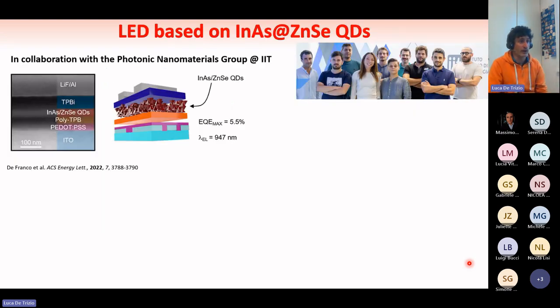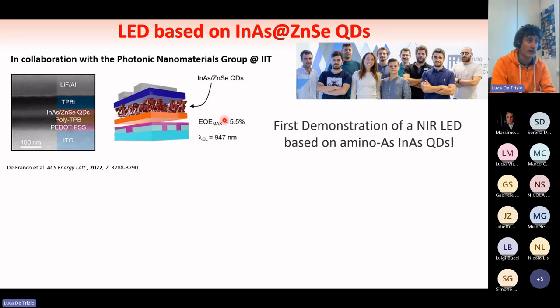So eventually, as we are aiming at devices, we employed our indium arsenide zinc selenide dots in real application like LED. This is the structure of the LED. This is a schematic representation of the LED. And we achieved initially an external quantum efficiency, so this is the efficiency of the device, of 5%, which represented the first demonstration of an IR emitting LED based on this kind of quantum dots.